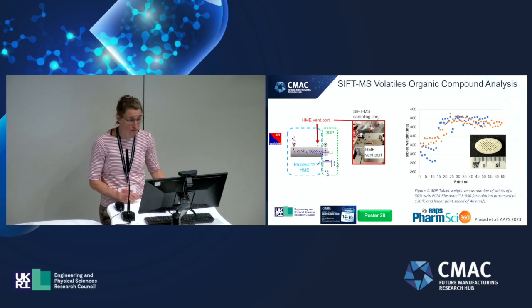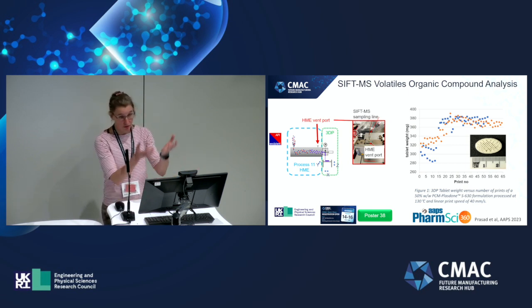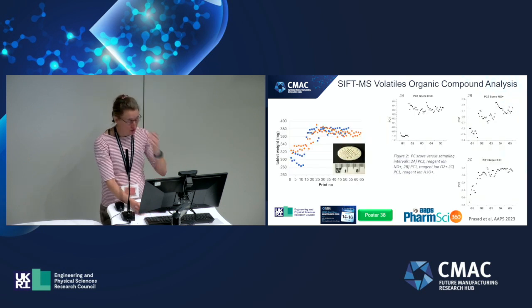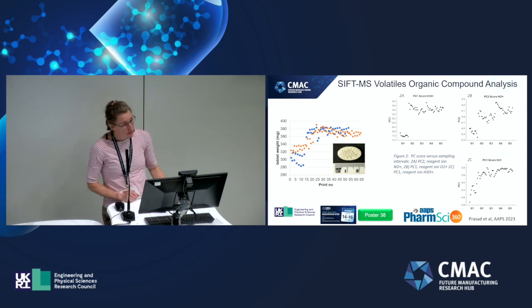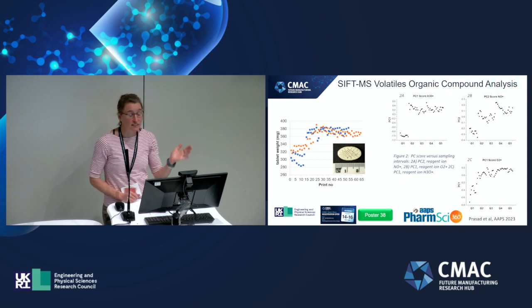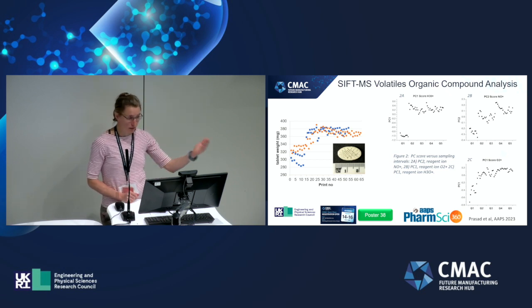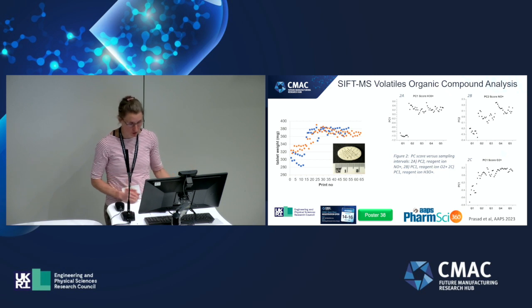that we have on site, with the idea to monitor the volatile organic compounds that come off the vent port during the manufacturing process. So this was a very initial trial, and we then collected a mass scan. We performed some principal component analysis on the data, and what I'm showing here on the right-hand side are the PC scores, so the principal component scores versus the sampling intervals, and what we could observe was that we actually have a very similar trend in the data, similar to the weight change during manufacture.